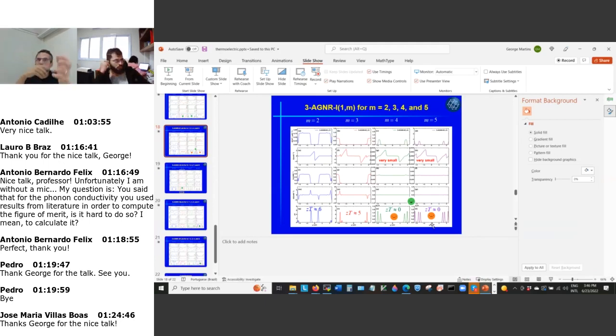So yes, you are looking at pieces of the transmission and the number of channels. You multiply the two of them, and in the case of S, you have to multiply by E minus EF, and it's this E minus EF that gives you the sign. So if the transmission and the number of channels is larger for E minus EF negative than it is for E minus EF positive, then the overall integral is going to be negative. But if it is the other way around, then it's going to be positive. And this is the reason why S obviously is an odd function of mu. Yeah, that's clear from the results.